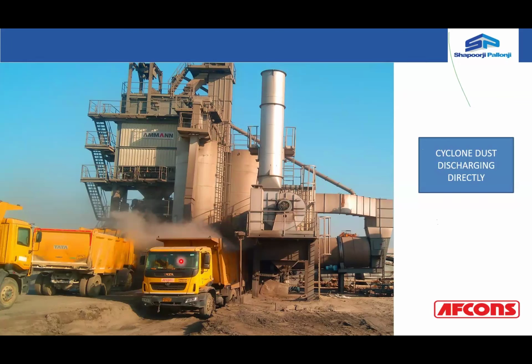Now, cyclone dust is basically a waste or a byproduct of the hot mix plant. If you see the photographs, the particle size of the cyclone dust is less than 75 microns, and it is a waste and difficult to control its disposal. So it is having environmental impacts also. Generally, the storage and the applicability is being tested in this particular study.